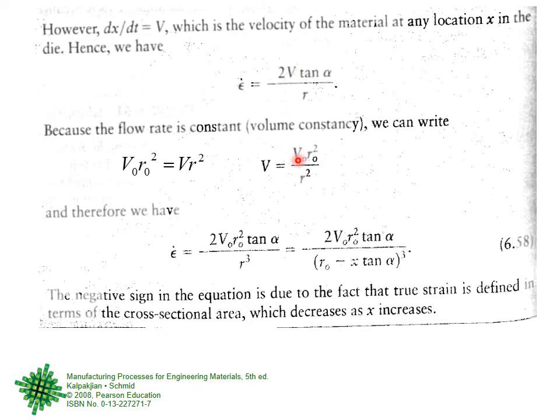Substituting V = V₀R₀²/R² into the strain rate equation, your final equation is: ε̇ = 2V₀R₀²·tan(α) / R³. And from the basic geometry, R = R₀ - X·tan(α). So the true strain rate is expressed in terms of original velocity, original billet radius, die cone angle alpha, and current location X along the die as the RAM moves.